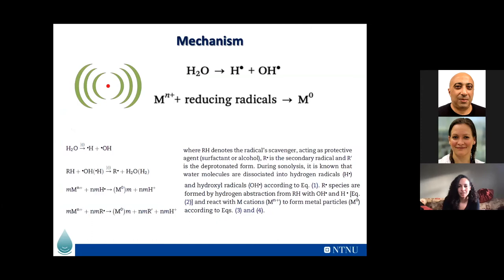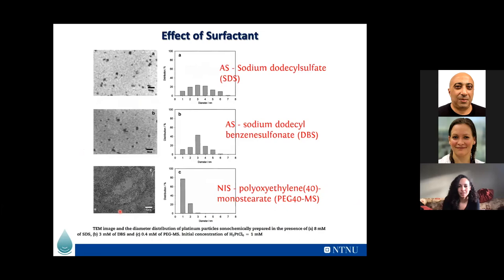Then if you had to use a different surfactant or alcohol, you go through different steps in order to get to your metallic state, stage zero. Also the effect of surfactant, which is a big thing. We looked at how we can use ionic surfactant and non-ionic surfactant, again in order to control the sizes. We found actually that with